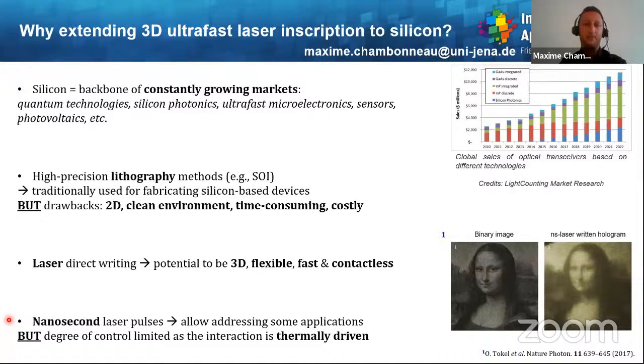To date, for laser silicon interaction, nanosecond laser pulses can be used, and they allow addressing some applications. As you can see here, there is a binary image of the Mona Lisa from Leonardo da Vinci, and this is what can be written inside silicon, the resulting hologram written by nanosecond laser pulses. Well, the main problem for nanosecond laser pulses is that the degree of control is somehow limited by the heat, and the interaction more generally is thermally driven.